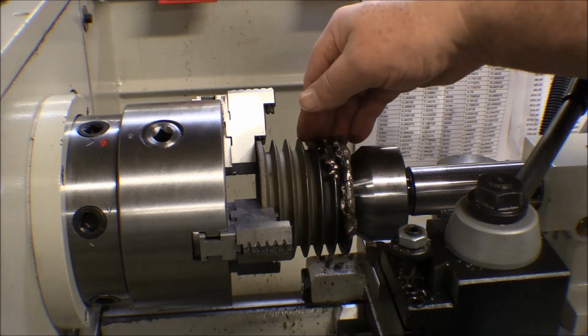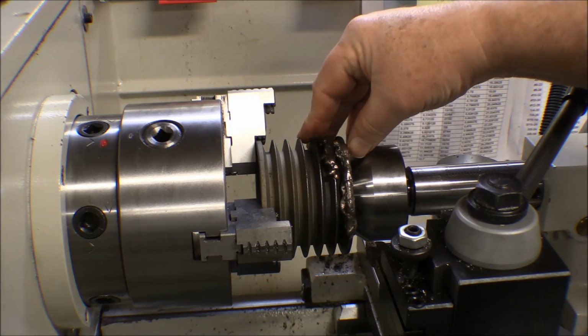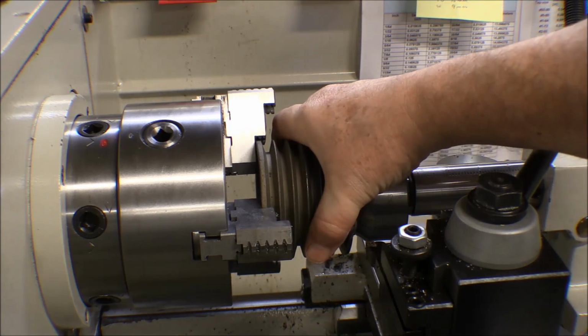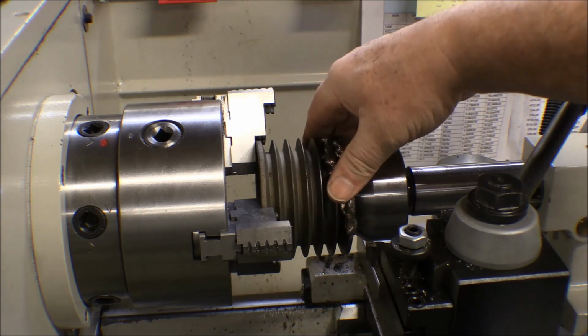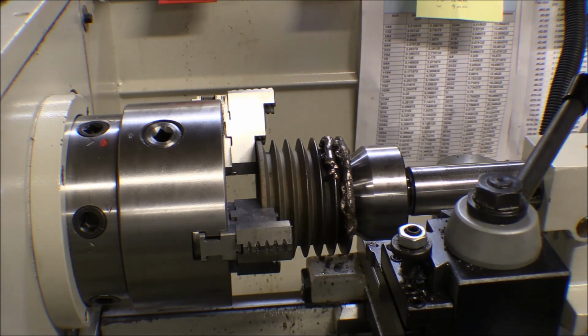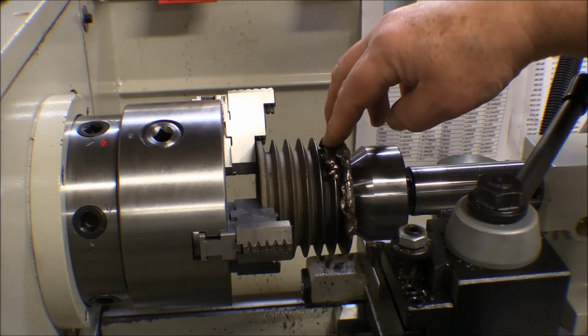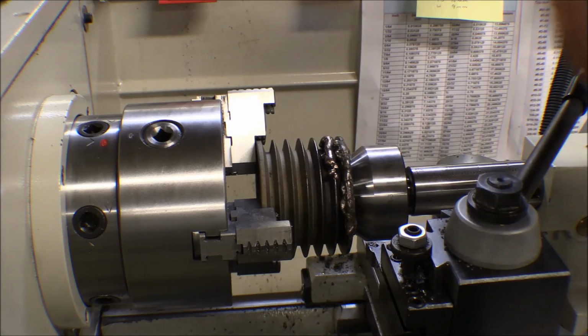This cast iron hub was pitted with rust and stuff, and that always has a tendency to oxidize out when you heat it up and you're trying to weld anything on it. I have a heck of a time with metal when it's oxidized out like that, when it's rusted like that. I might start pushing it too fast. I start heating things up, and then I'll put the rod in there and start melting it, and then it BBs up on the stuff. And anyway, I got it. We'll see how well it holds up as I start machining it down.